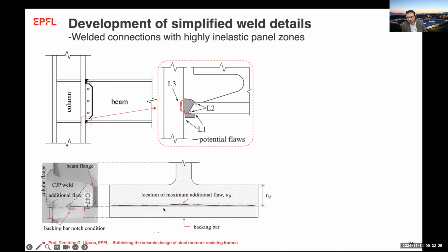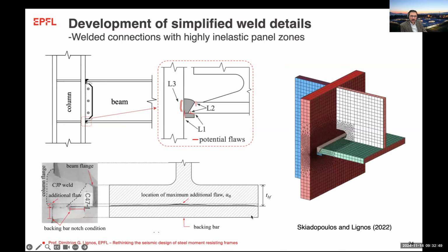And this is a snapshot from a pre-Northridge connection. Usually we like to remove the backing bar here because what happens behind it is that you may have a flaw that is running across the flange. And if the flaw is large, then this is essentially a region where the risk of fracture is going to be very high.